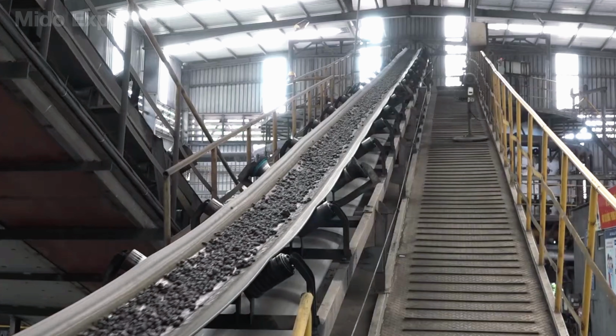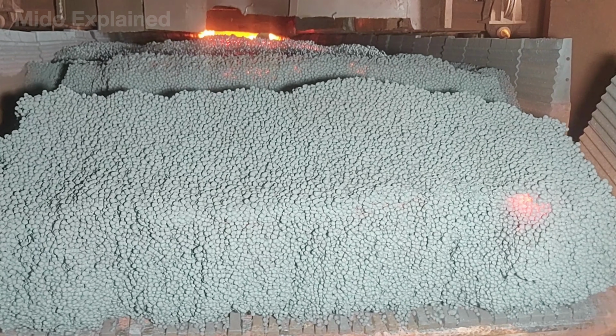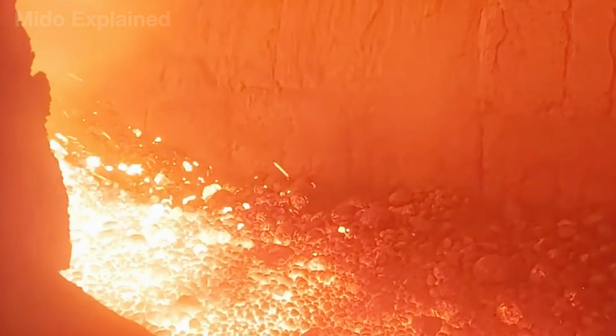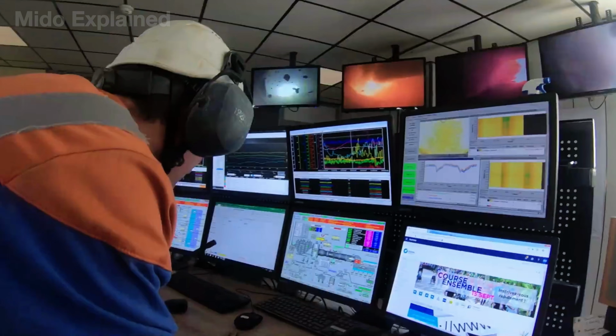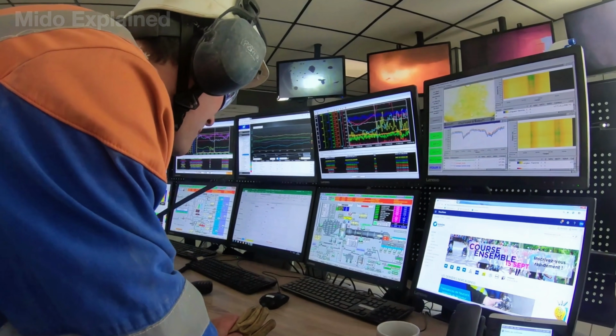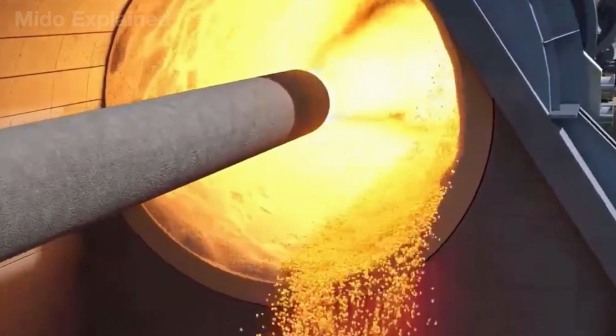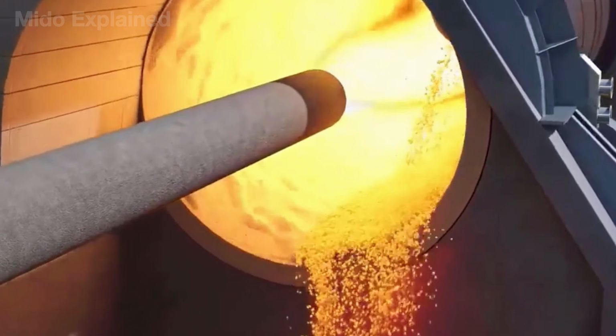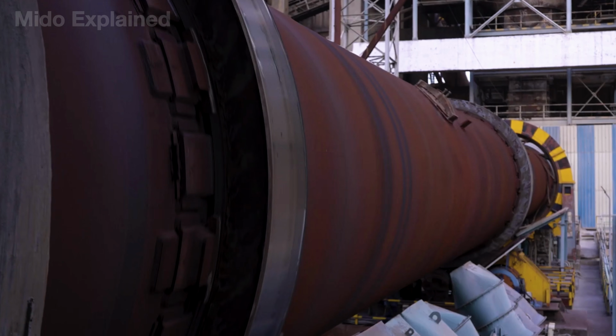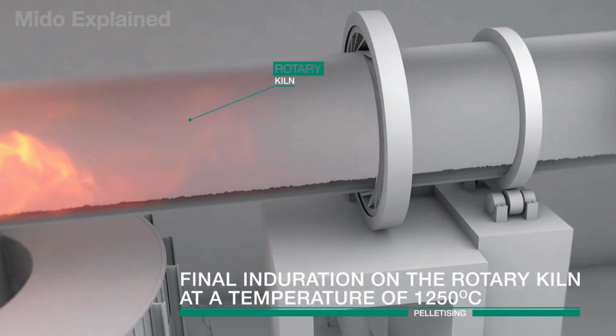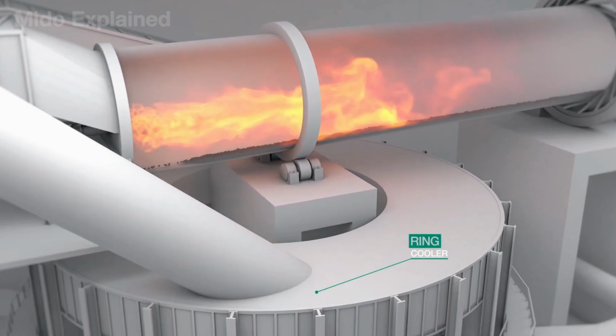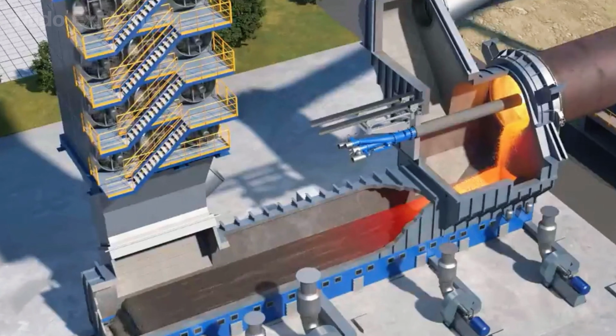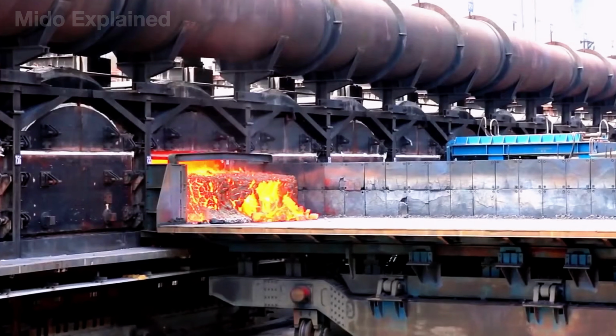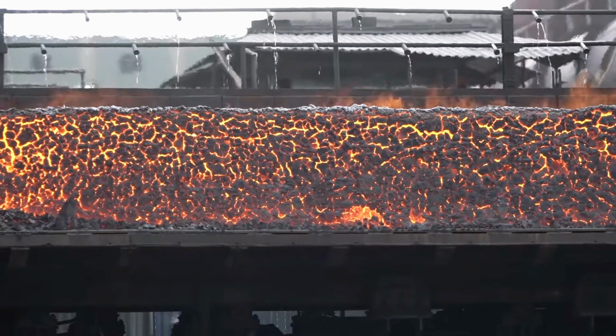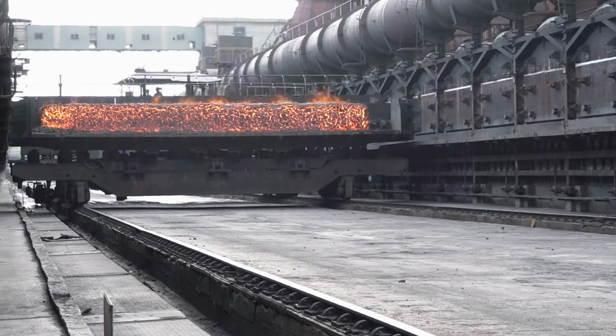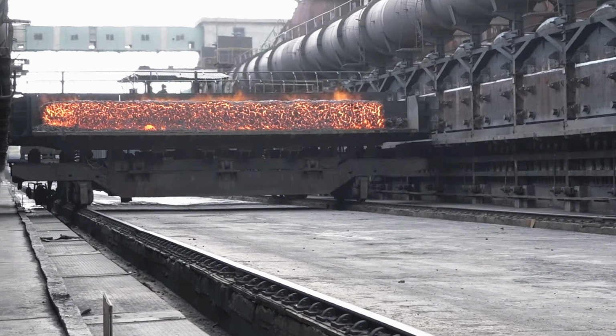To become sufficiently hard for steelmaking, the ore pellets are placed in a furnace. Here, the temperature is raised to over 2,300 degrees Fahrenheit, enough to cause the ore particles to bond tightly together without melting them. During the heating process, each pellet shrinks by about 10%, becoming much denser and harder than its original size. After controlled cooling, a standard pellet can withstand a compressive force of over 550 pounds. This strength prevents them from breaking during transport and maintains their shape under the weight of thousands of other pellets inside the blast furnace.